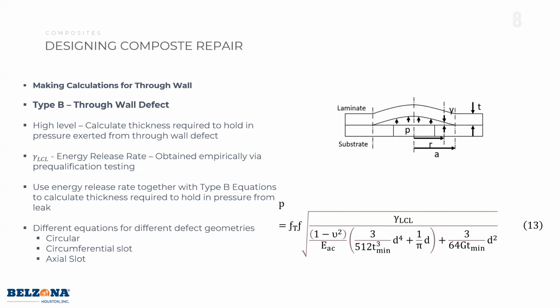So this equation is very, I like to say, realistic because it's based on empirical data. This energy release rate, which is in this equation here, the lambda LCL, was obtained via testing, and we do the testing by doing leak repairs on spools. So we have a spool with a hole, we pressure it up, do several sets, and obtain that variable. So it's a very real-world application, and also a lot of safety factors are thrown in there.